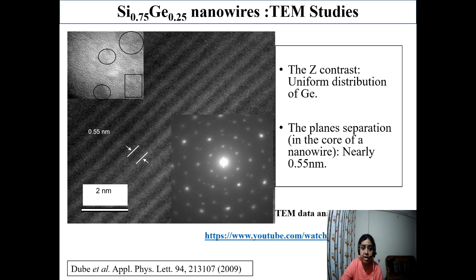And again here you can see some bright image, some dark image. This is a contrast. This is basically silicon germanium alloy nanowire. This I have given from my PhD thesis. There I have synthesized silicon germanium alloy nanowire. So in fact TEM analysis confirms uniform distribution of germanium in silicon. Here you can see some dark images because the atomic number of germanium is higher than silicon. So whatever is brighter place, that is confirming the presence of germanium, and other is silicon. So germanium is uniformly distributed in silicon.